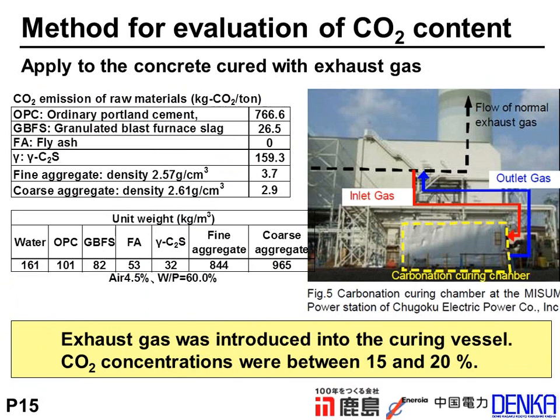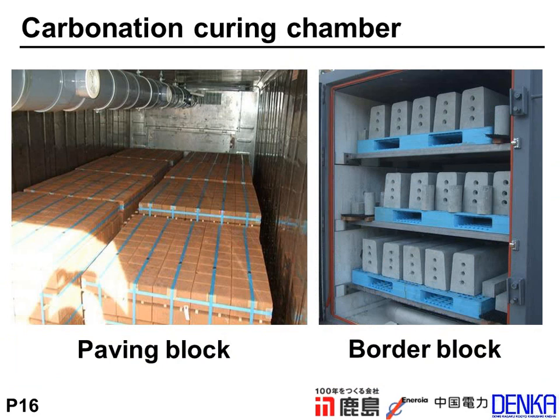And the right picture is the carbonation curing chamber at Misumi Power Station of Chugoku Electric Power in Japan. This yellow part is the carbonation curing chamber. The exhaust gas was launched into the curing vessel, this carbonation curing chamber, after adjusting the temperature to 50 degrees Celsius and the relative humidity to 50% along this red arrow. And the carbon dioxide concentration was between 15 and 20%. This picture is inside of the carbonation curing chamber, and the paving blocks and border blocks are cured in this chamber, like this.